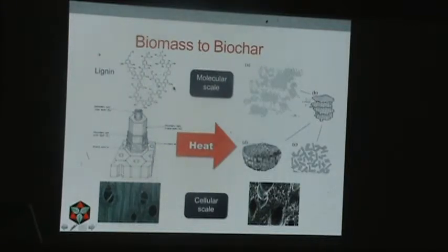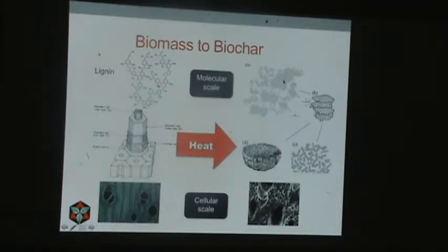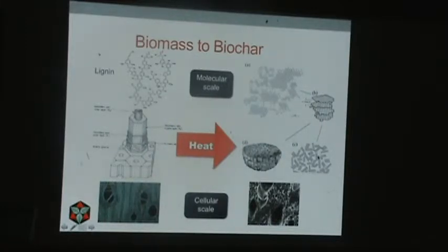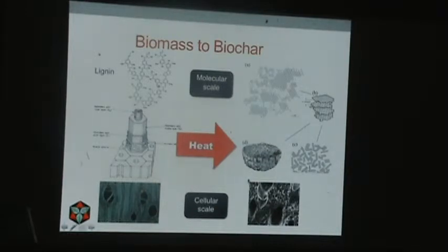When you add heat, all these other things that are attached — the hydrogen and oxygen — vaporize, and the carbon molecules link up into these fused rings. They tend to form these little sheets, and kind of zooming out a little bit, they'll jumble up together into these little sections of what we call graphene sheets. A biochar particle might look like a whole jumbled bunch of these little graphene sheets.